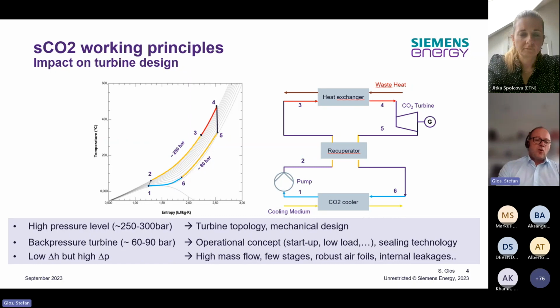Then we have a comparably low expansion line, meaning we have quite a low enthalpy drop, but a significantly high pressure drop. And from the low enthalpy drop, you can conclude that you need a high mass flow circulating in the system. On the other hand, you will get quite few stages, at least significantly fewer than in a steam turbine, but these stages then have to deal with that large pressure drop. That leads to robust airfoils, and furthermore, the internal leakages become more important, and you have to take care of that as well.